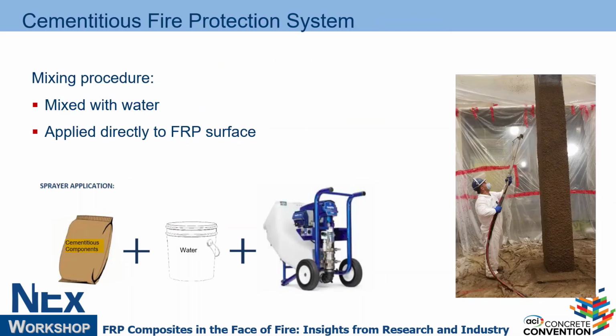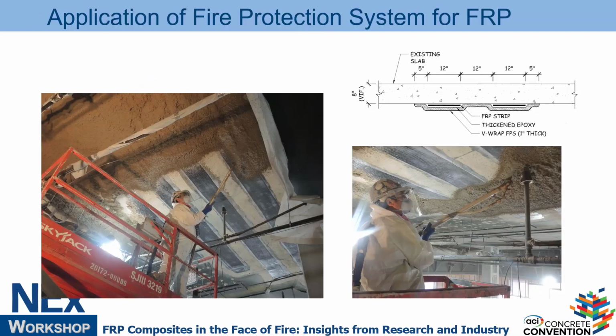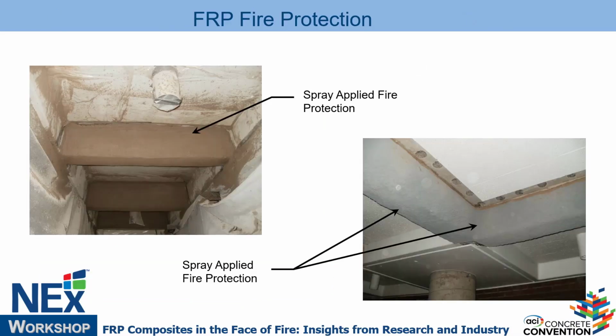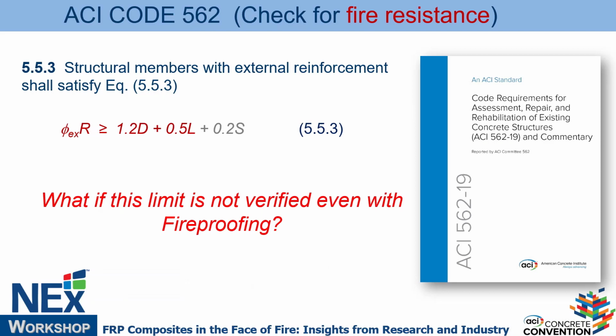Fire protection system, most of the time, is a mix of different cementitious components with water, and you can spray apply it. You apply it to the FRP. I mentioned the thickness between 3/4 inch and 1 inch, so it's not a significant change to the structural element, but it's enough to provide adequate fire protection. Here are some photos of elements that have been spray applied over FRP.